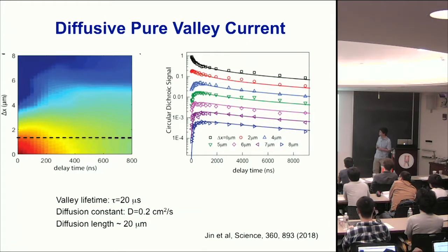And this is not quite trivial in this system, because in transition metal dichalcogenides, a very large experimental challenge is to make a good contact. If you don't have good contact, it's very hard to measure transport property and determine the mobility, especially at low temperature and when the carrier concentration is very small. But here, this is a completely contact-free detection. By a purely optical technique, just with spatially and temporally resolved measurement, you can directly determine the propagation of charges and spins in the 2D system, and you can use it to extract important transport parameters.